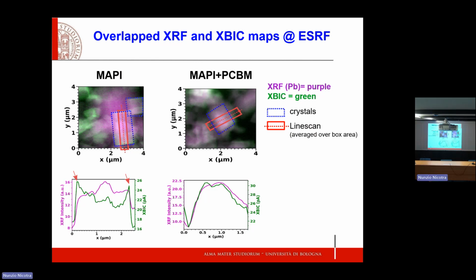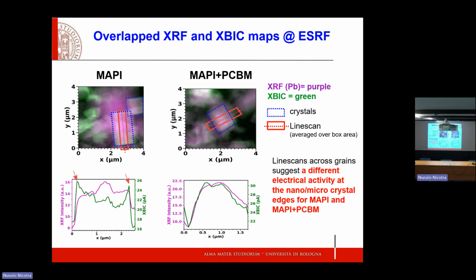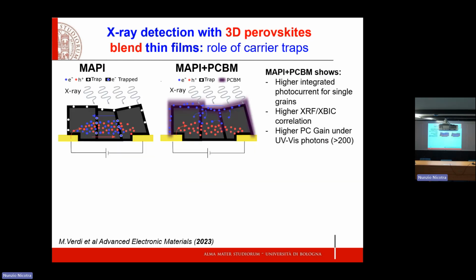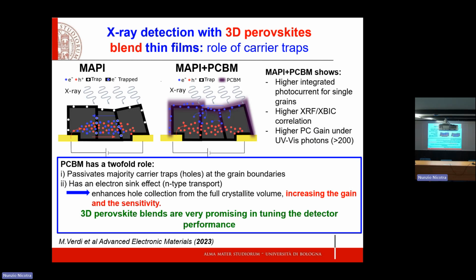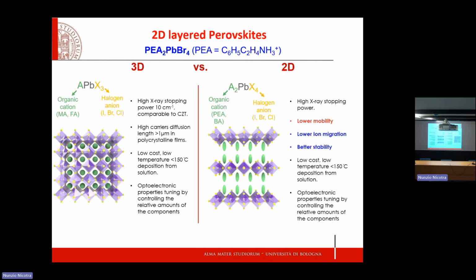Why is this happening? It is happening, again, because there is a different electrical activity in the blended material, where the polymer passivates the polycrystals, compared to the regions where there is no polymer. This is basically what we achieve. So the message is, if there is the polymer, it can passivate nicely all the grains, allowing for much better transport of the created electrical carriers through the grains and from one grain to the other. So again, to conclude, we realized that both in perovskite and organic thin films, the physics of the electrical defects and their interaction with the incoming radiation was really important.